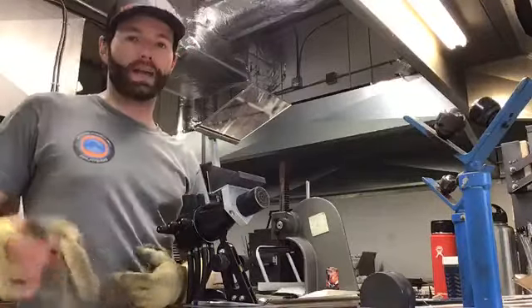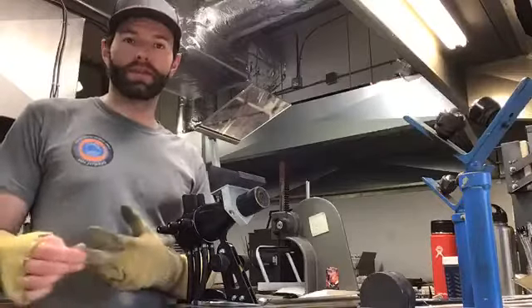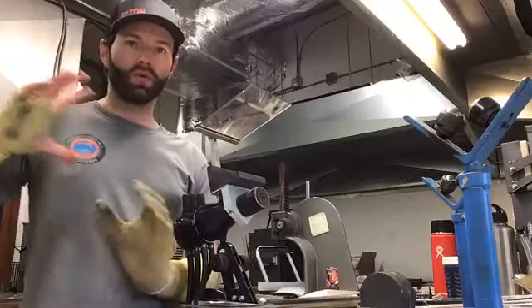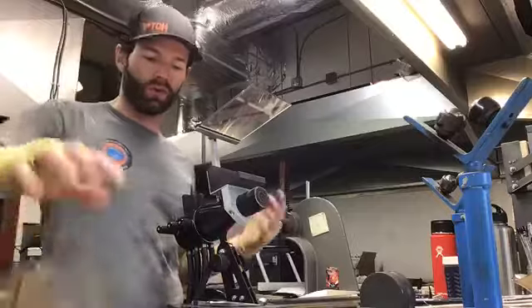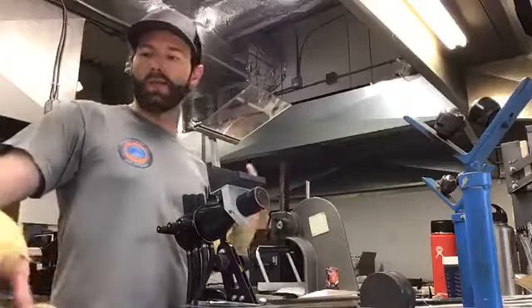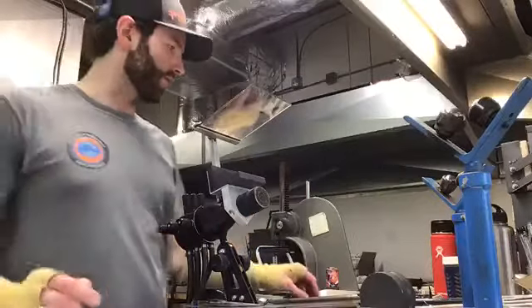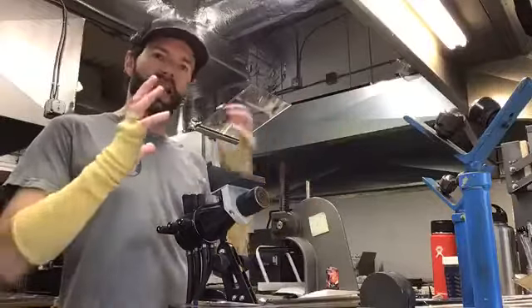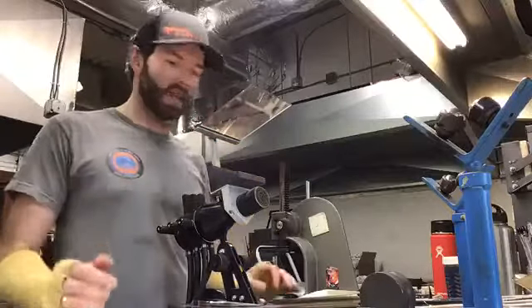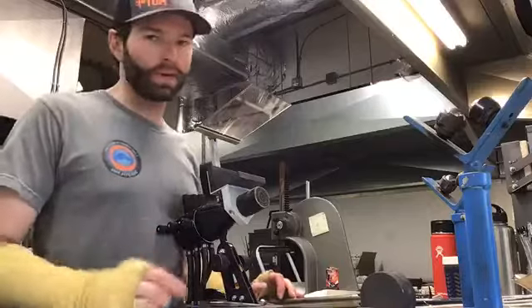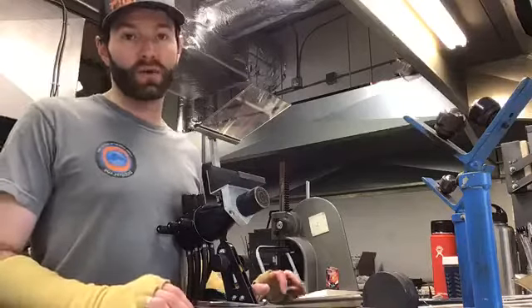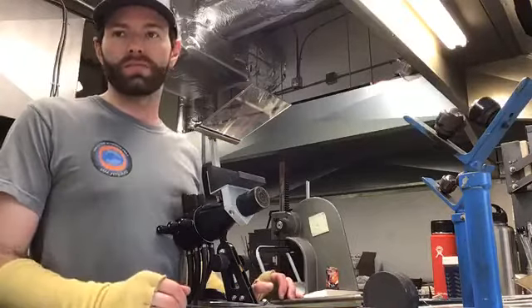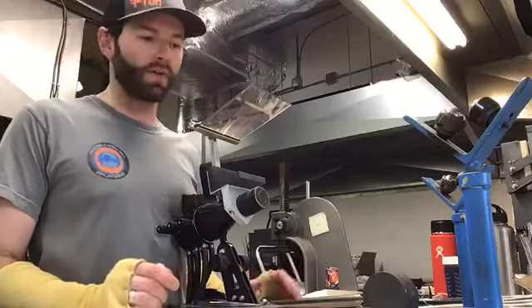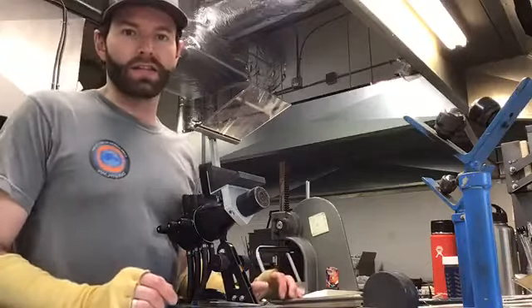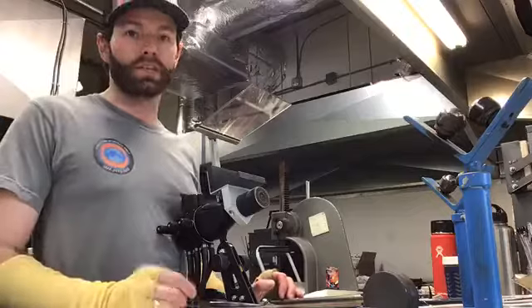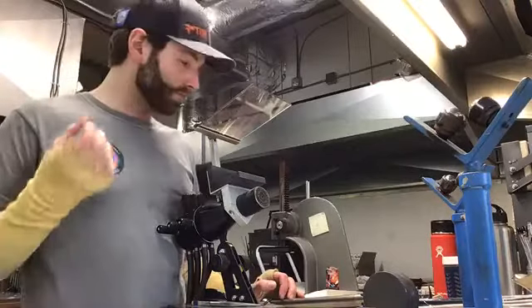If we were to let it cool on the bench here, it would just start cracking in about, I don't know, 20 minutes or so, because that outside is going to cool way before the inside does, and when it cools, just like anything, it shrinks, and that builds up stress within the glass. So the kiln drops it slowly, so the outside and the core all shrink at the same time. Super microscopic level. It's not like ceramics where you're going to lose 5% of volume or whatever the math is on that. It's nothing we can see with our eyes, but that's what the glass is doing.